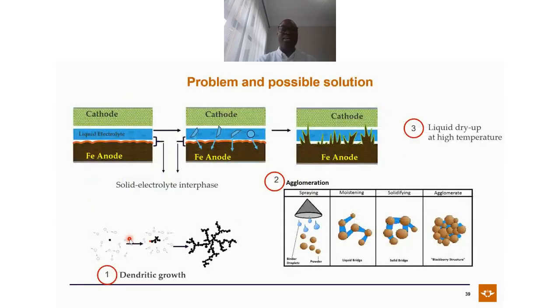Well, if you have liquid electrolyte, there are three things that happen. First of all is the formation of dendritic growth. If you have iron anode, which is grounded powder, and you have liquid electrolyte, with time, this liquid electrolyte comes into the grounded powder and it makes what you call dendrites. So most of this liquid, when it comes in, ends up forming this type of orientation. And this is bad because of short-circuiting, and this part indicates that the OH will no longer be able to be transported. This is the dendrite growth, which we do not want.